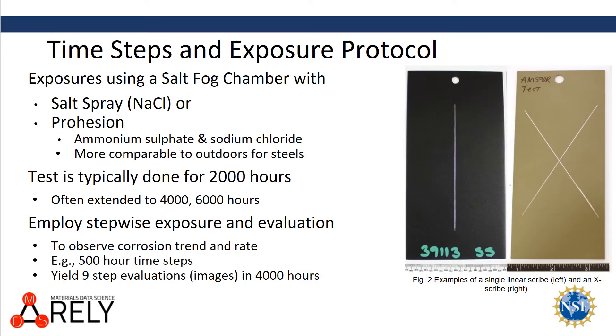The time steps and exposure protocol for this project will include a salt fog chamber with salt spray or prohesion. This test is typically done in increments of 2,000 hours, but here we'll employ stepwise exposure and evaluation in 500-hour time steps to observe the corrosion trend and rate. This would yield nine step evaluations, or nine images, in 4,000 hours of exposure.